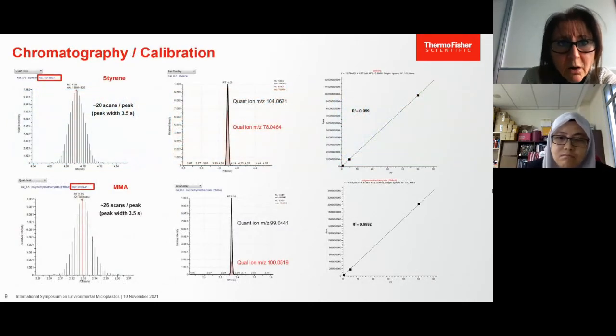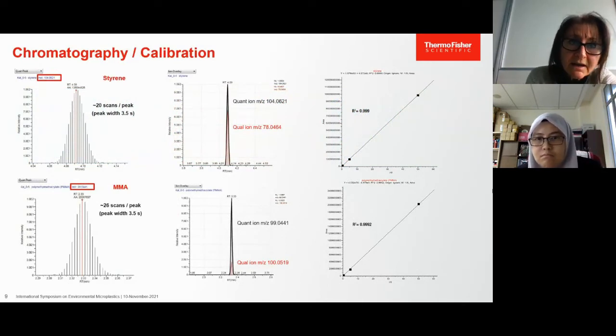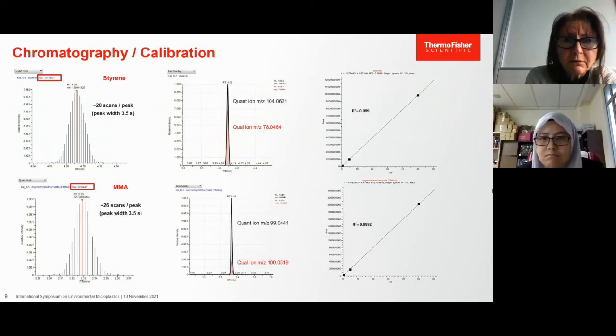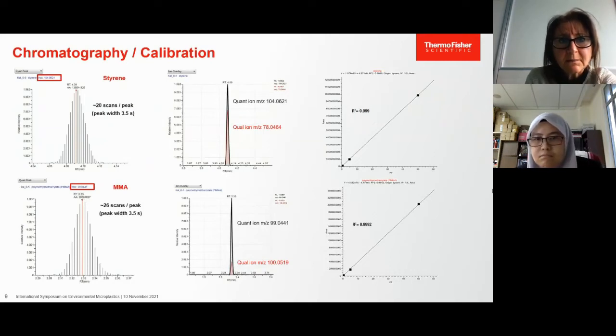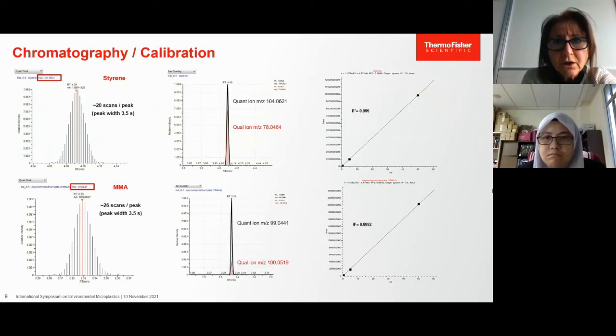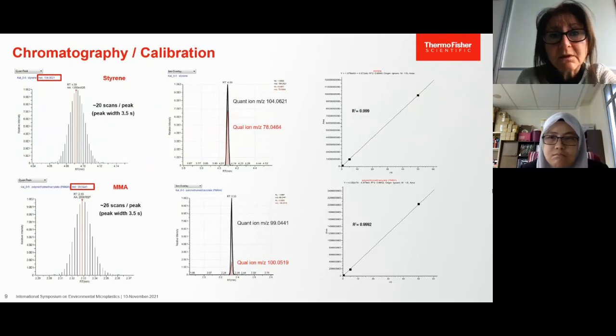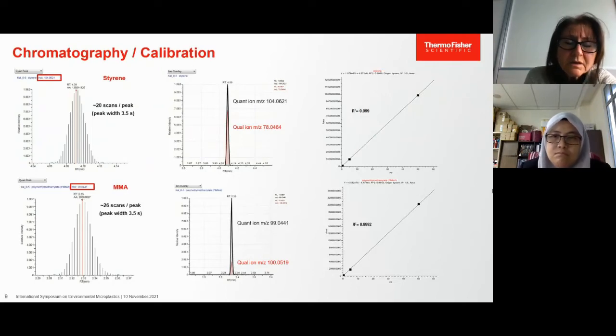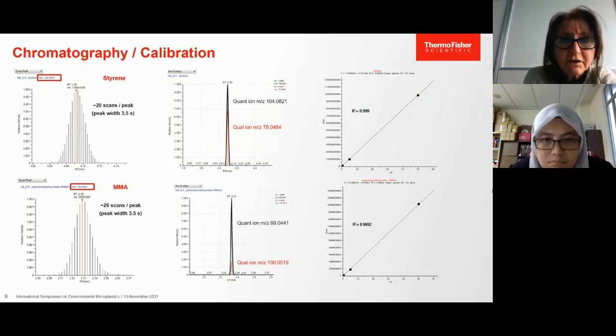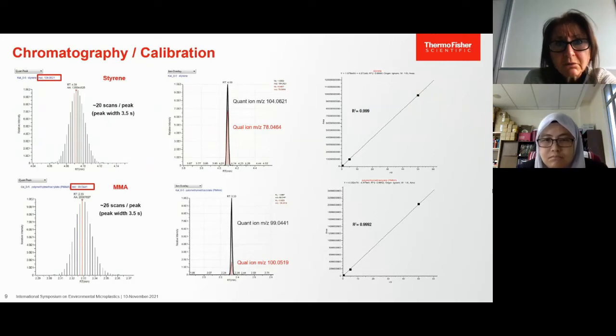As I mentioned, the acquisition has been done in full scan. And here you can see the extracted ion chromatograms for styrene and methyl methacrylate, which are used to assess the response linearity. Linearity was tested using polymer standard at a concentration ranging from 0.05 to 50 microgram, which is the range that corresponds to the amount found in real samples analyzed with pyrolysis GC-MS.